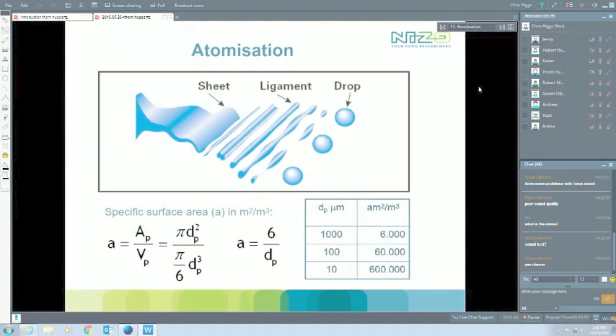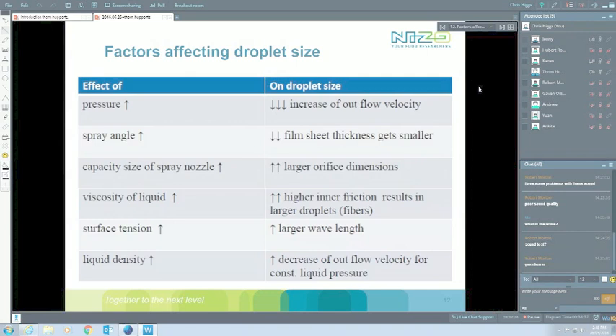Of course, what we need to look at during atomization, if we want to understand what is happening to our product, we need to consider that the first thing that we end up doing there is basically forming a very thin sheet of the material, extremely high shear, of course, at these conditions. That will break up into ligaments, and that is actually going to break up into droplets. Everything happens extremely quickly. Forces are very high, the shear is very high that it encounters, and that, of course, also causes issues with stability.